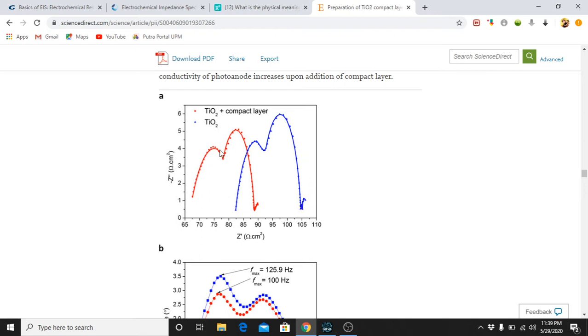So from the Nyquist plot, the important thing that you can extract is, first one, the RS. This is the RS, the resistance that intersects with the x-axis, the series resistance. And also the charge transfer resistance. In this case, we have two, one RCT and RCT2. So you get the RS and also RCT. That is the most basic thing that people want to find out from the impedance analysis, from the Nyquist plot.